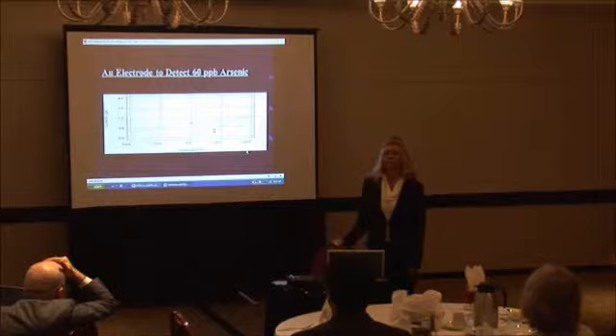And this is just an example of arsenic water. Basically, in the arsenic water, they had various concentrations. This is an example of 60 ppb detected. And so another module created was, can you detect arsenic in water? And when you detect arsenic in water, what type of electrode do you want to utilize? If you actually took a platinum electrode, you would see no peak. Like, there would be no arsenic peak. This is an arsenic peak right here. If you come down, this is the arsenic peak. But if you would have done a platinum electrode, you would get no detection. This is actually a gold electrode.